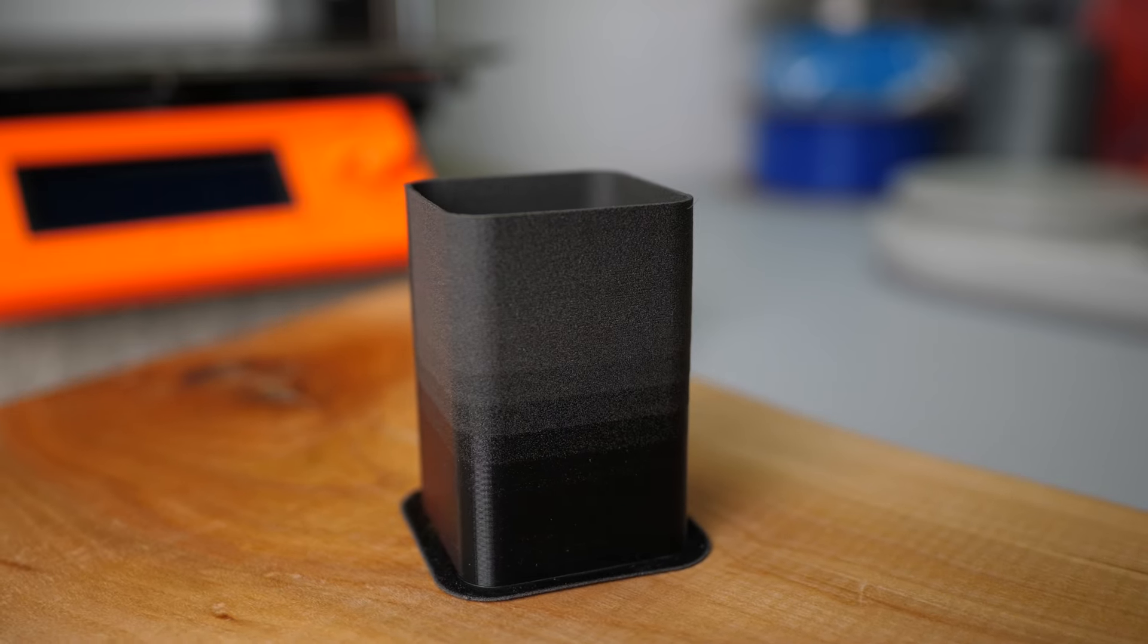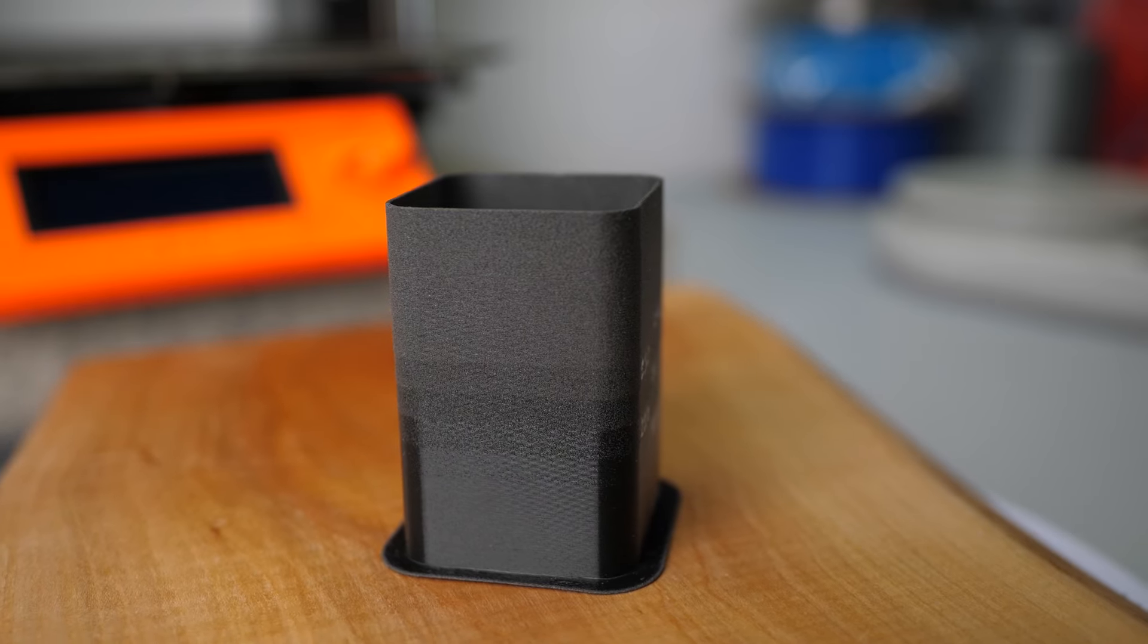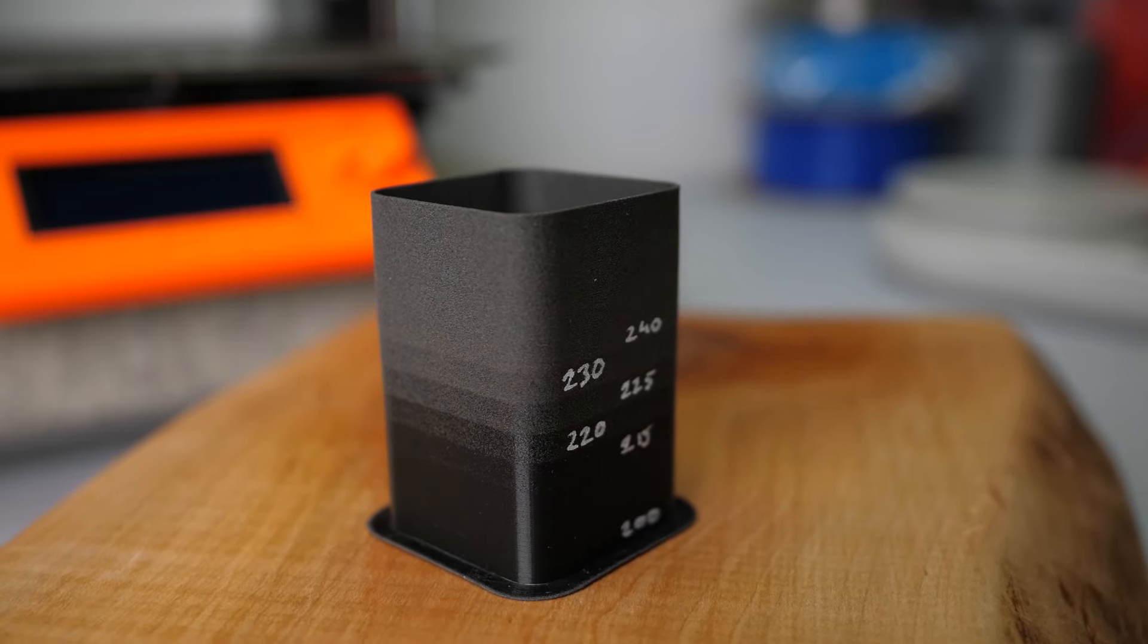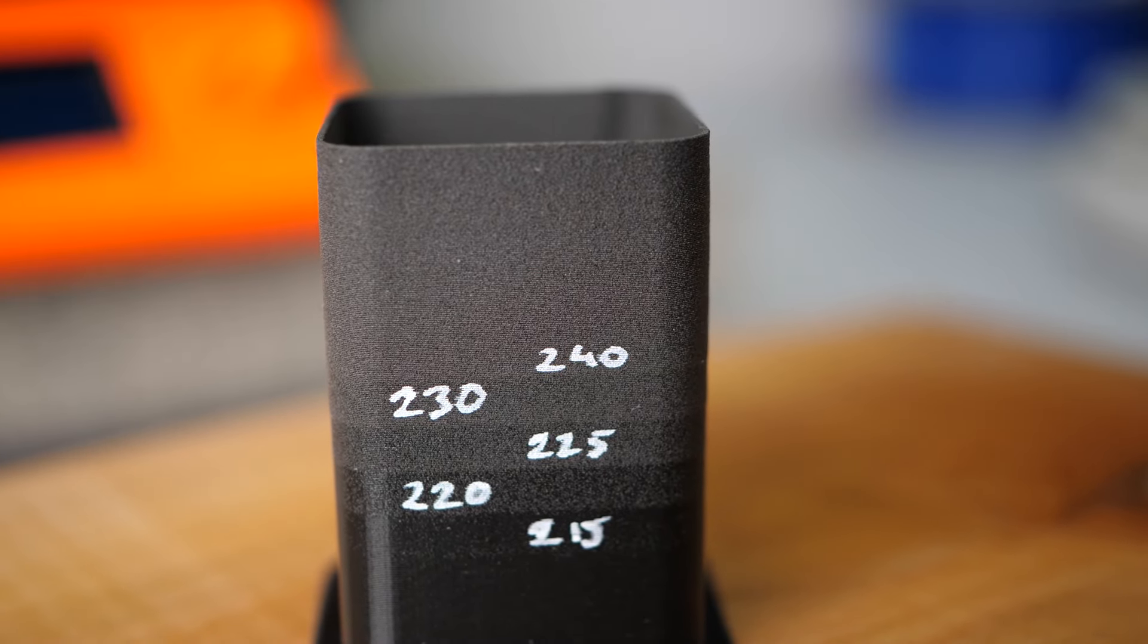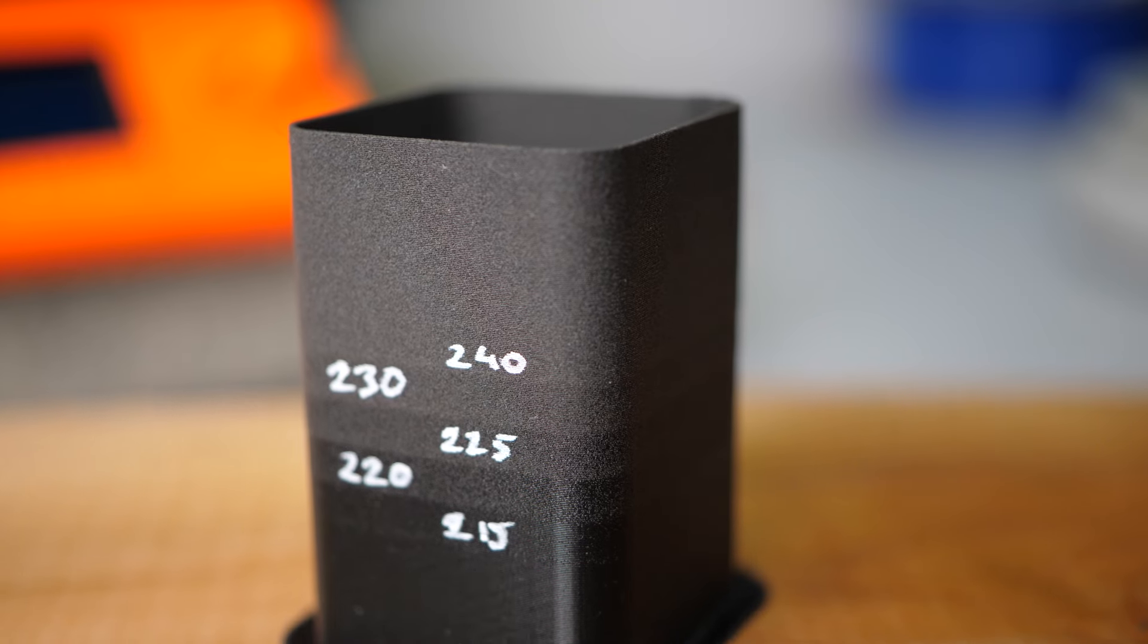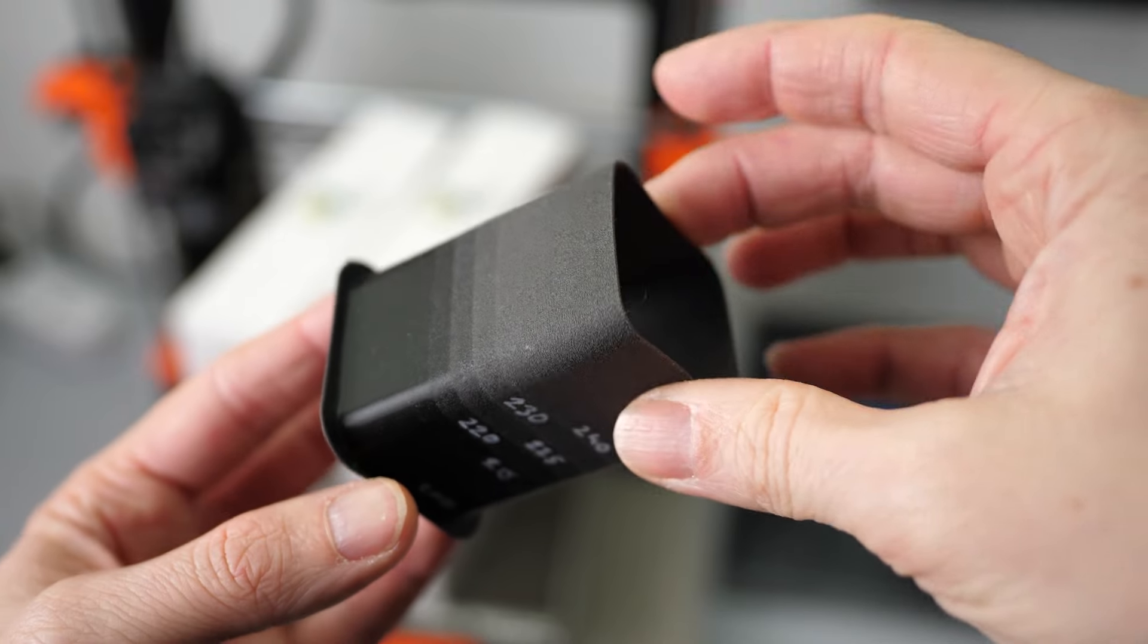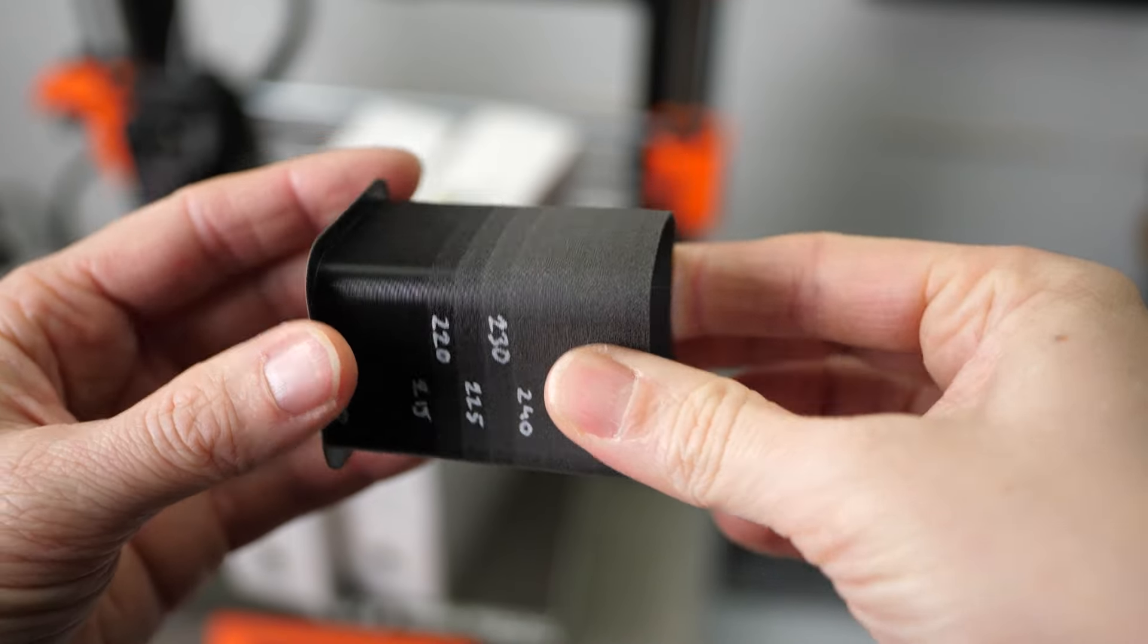In order to see how the material generally performs, I printed a simple single-wall test part on which I first varied the nozzle temperature in 5 degrees steps and later in 10 degrees steps starting from 200 degrees Celsius to 280 degrees Celsius. All the way up to 210 degrees Celsius the material looks like regular PLA. At 215 degrees Celsius you start noticing small bubbles on the surface that seem to get more and more up to 250 degrees Celsius at which point it looks fully bubbled up. First impression handling it is already really nice since even the part printed at 280 degrees Celsius still looks very flexible.